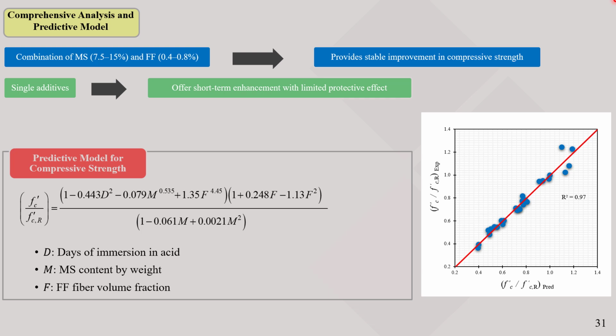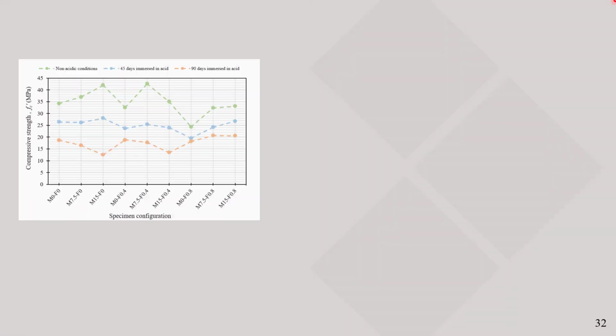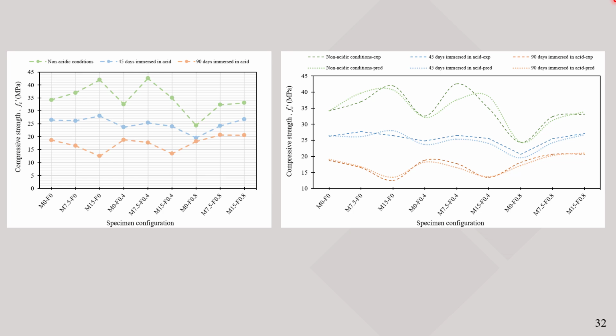The compressive strength of the reference sample under non-acidic conditions was considered as a baseline. Model parameters included the number of days of acid immersion, the weight percentage of microsilica, and the volumetric percentage of Forta-Ferro fibers. The predictive model showed good accuracy. Comparative charts between experimental results and the model, as well as response surface plots, were provided.